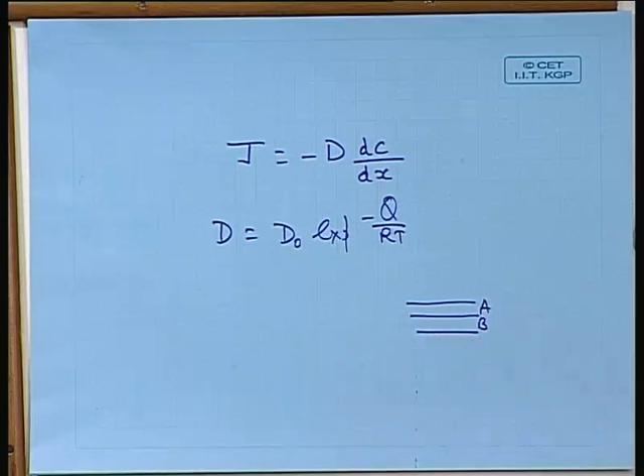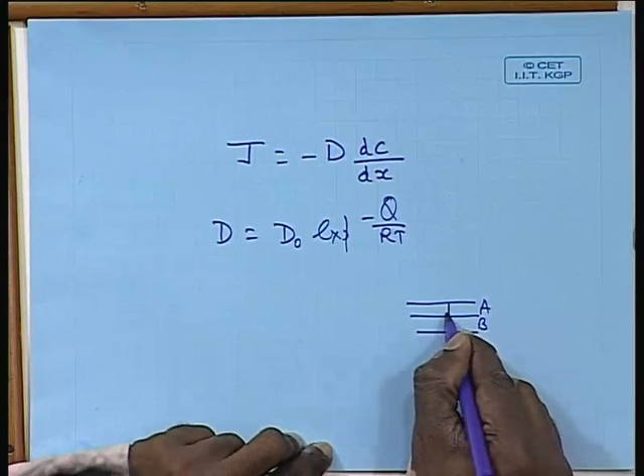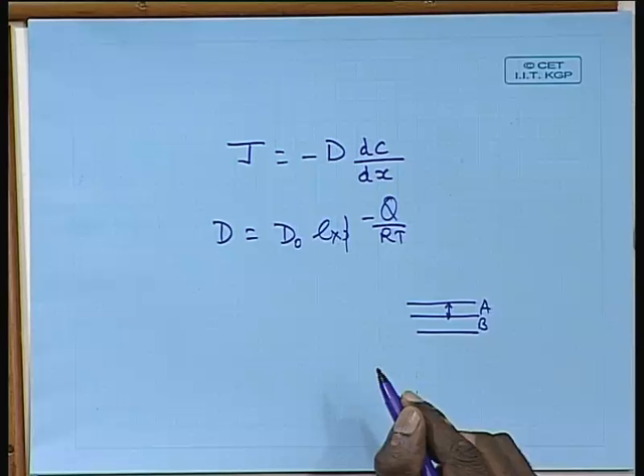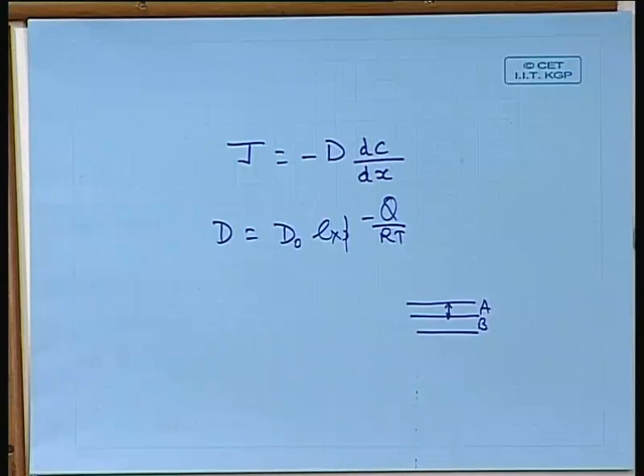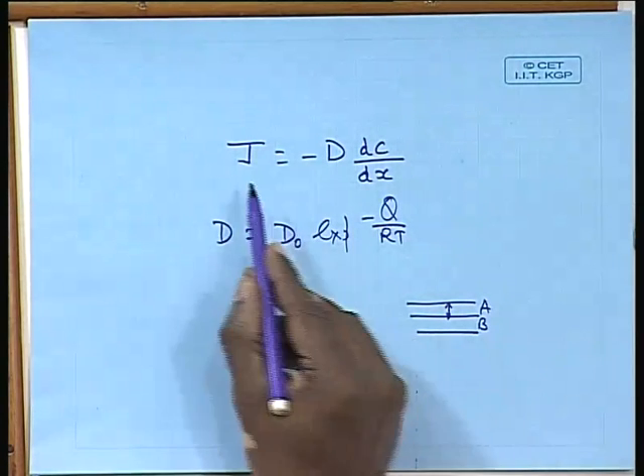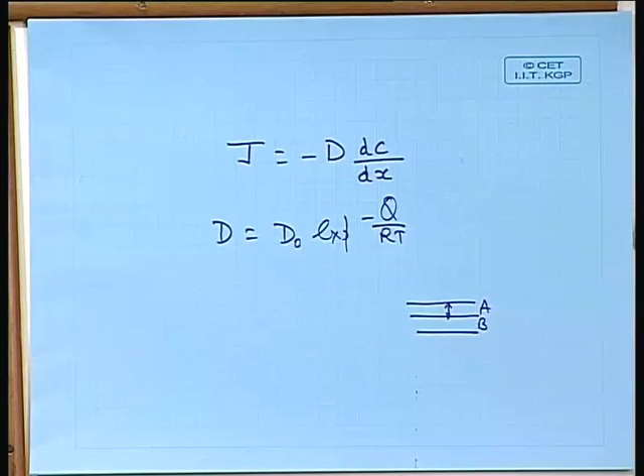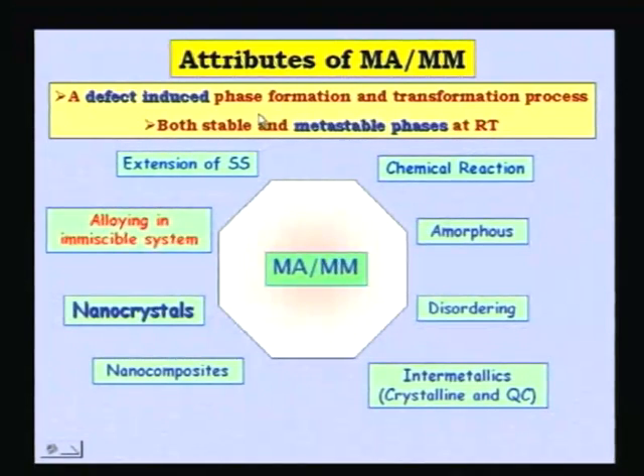In a layered structure like this, the diffusion has to occur over this thickness, isn't it? So if that thickness can be reduced, then the dx is decreased, and if the denominator decreases, then the whole fraction increases tremendously, and as a result the flux increases. So that is one of the reasons why you have the defect induced phase formation and transformations which get enhanced because of the defects and the decrease in the size of the crystals that occurs during ball milling.